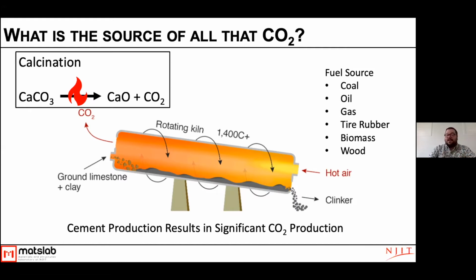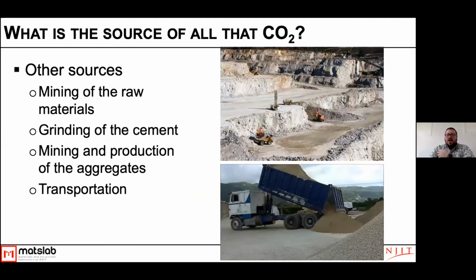Because we have this process called calcination. The limestone that we have to use as a raw material, we need to break down to get calcium oxide. And that is one of the most important components in cement. When we break down that calcium carbonate or the limestone, the CaCO3, we heat it up and we release CO2. And that CO2 mostly gets lost to the atmosphere at the moment. There's a lot of new technology that's being developed to try to capture that as well. That hopefully will be coming on in the coming years. But for right now, that's a lot of CO2 that gets produced from this system. Other sources outside of that, of course, are mining and transportation, but these are minor compared to what is coming out of the kiln just from the chemical process.